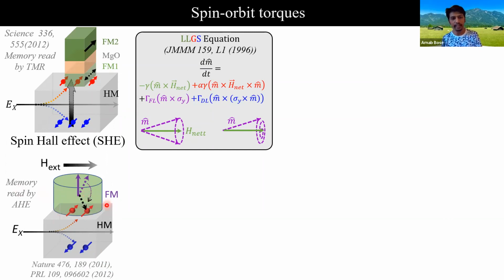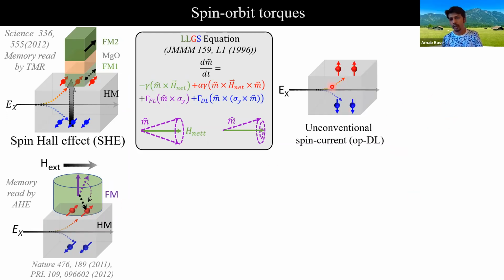In this case, only a single ferromagnetic layer is enough for the reading. For example, the magnetic state can be read by the anomalous Hall effect. Here, we see that already we need to do some tricks, for example, applying an external field or exchange bias to achieve deterministic switching. So ideally, we would require this sort of case where in-plane electric field or in-plane current can generate out-of-plane spins flowing in the out-of-plane direction. Then these spins can directly produce out-of-plane antidamping torque on the adjacent magnet, and it can produce very efficient spin orbit torque-based switching. So the generation of out-of-plane spins from in-plane current that flow in the out-of-plane direction, I call unconventional spin current that produces out-of-plane damping-like torque.